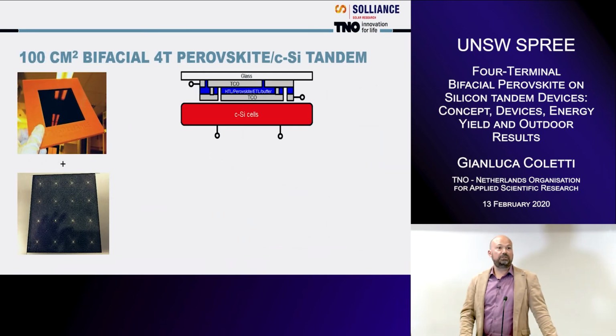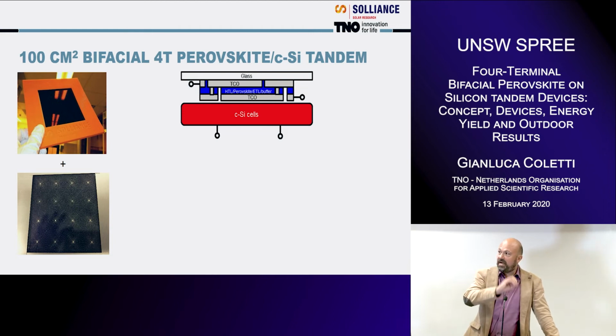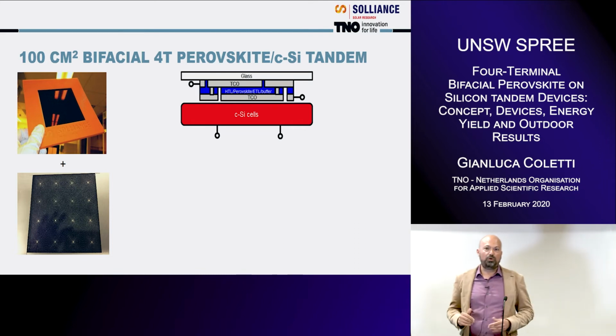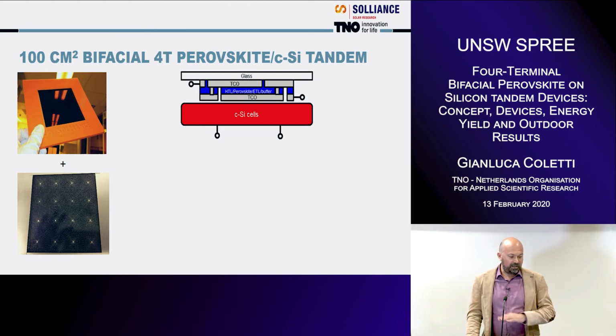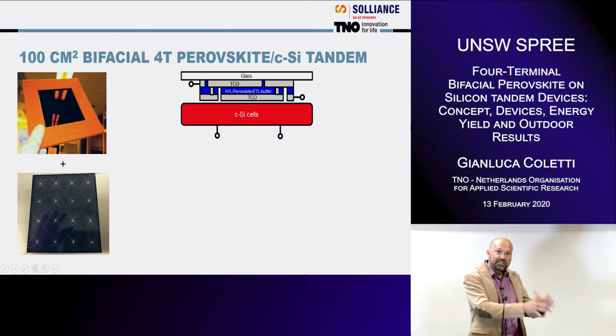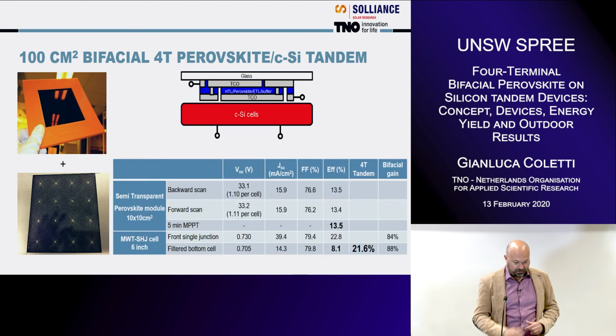So next is about, let's say, scaling up of this technology. The perovskite cell is a single cell that I showed so far, then I showed the mini module result. But essentially at Solliance what we do is design the material and all the layers as a single junction, as a single cell device, and then transfer them to the full module size. And here is a glass sheet of 6 inch, where there is a device of 100 square centimeter, as you see in the picture, made with the same material used for the single cell.